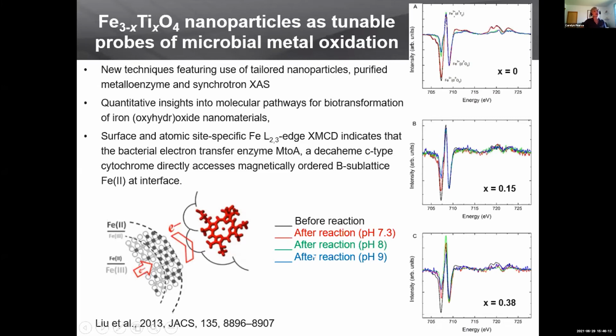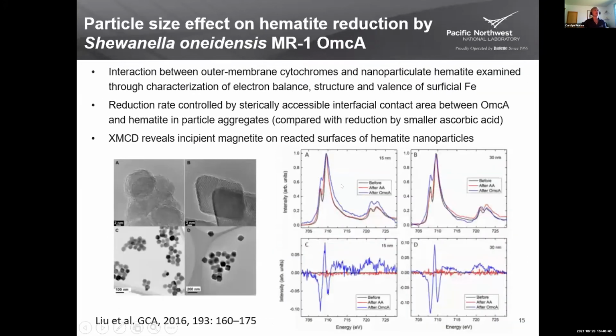And we characterized this reaction as a function of pH, and really demonstrated the influence of the cytochrome over just changing the aqueous conditions at that interface with the titanomagnetite nanoparticles. So this was the first time we could really get quantitative insights into these molecular pathways for these biotransformation reactions using just enzymes and these tunable iron minerals. So that was iron oxidation.